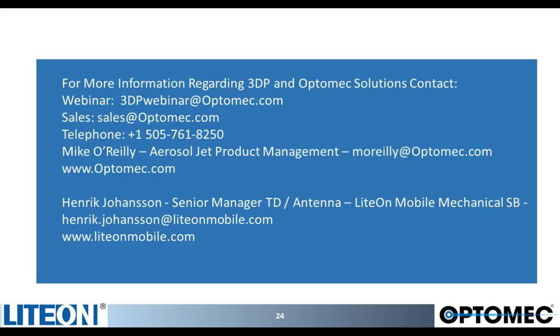Another strength of our technology is because of what we call sheath gas, basically the curtain that surrounds the nozzle, we very rarely have fouling of the nozzle, which is a common problem with inkjet, where the piezos get plugged up with material pretty rapidly, and you need to then start firing out of another hole. Our system works in a continuous fashion, meaning we're a continuous flow system, so we can print for hours at a time without any interruption to the process.